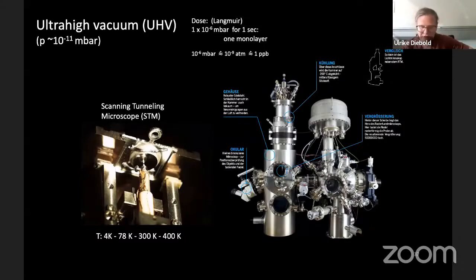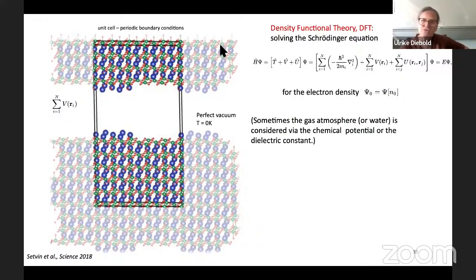But how does it relate to anything? In DFT calculations, if you think about it, to solve the Schrödinger equation, right, this is the kinetic energy of the electrons. This is the correlation and exchange between different electron-electron interactions, the hard part, that's all put in this functional. And then here you have this interaction between the atomic cores and the electrons, right? It's the so-called easy part. So for example, when you do surface calculations, you set up a cell as big as you want, as your computer allows you to within reasonable computing time, and you put some vacuum in between, and then you minimize this. You change the energy until you have a minimum, and then this is the surface structure.